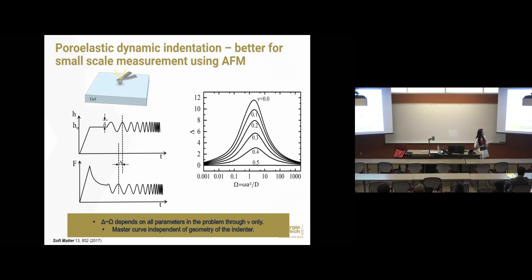Just to make a long story short, we actually found a master curve for this problem as well. And this time, it's even simpler. It's independent of the shape of the indenter. No matter what shape of indenter you use, the behavior should follow the master behavior you see here. So delta is the phase lag when you apply this displacement sweeping through different frequencies, measure the force as a function of time. So you get this phase lag as a function of frequency. And if we normalize this frequency, all the curves should collapse into this curve you see here.